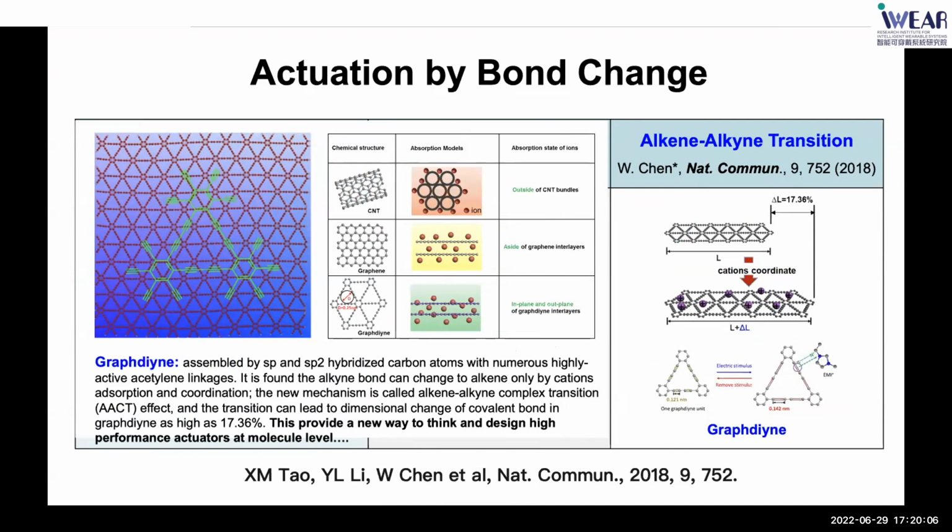We also found that the alkyne bonds can change to alkene bonds only by cation adsorption and coordination, and this can be achieved with only several volts.